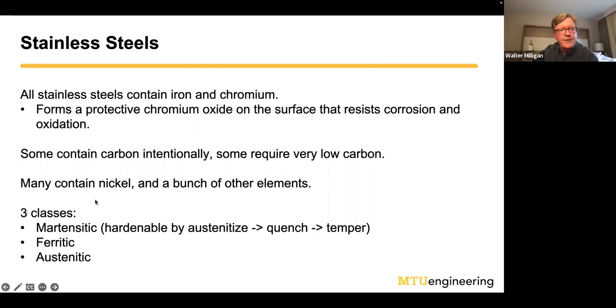So there are 3 basic classes. We can have martensitic stainless steels, and they are hardenable, just like we showed in the carbon steels. And the process is exactly the same. We have to austenitize and then quench and then temper. The carbides that we get are different. They're not Fe3C. I'll talk about that in a bit. But these are hardenable and very high performance for knives and shovels and horis and things like that. We can have ferritic steels that are not hardenable. They're much more low cost and much more affordable, with moderate corrosion resistance. And we can also have austenitic stainless steels, which are more costly and much more corrosion resistant.